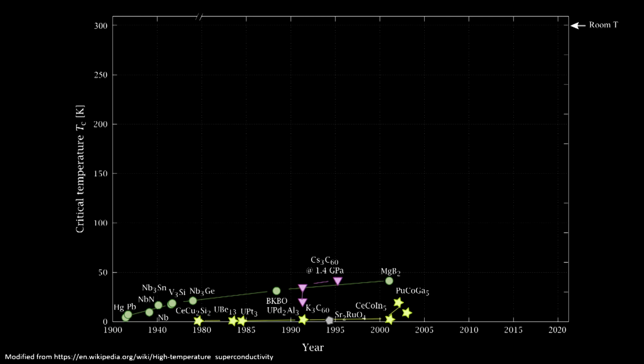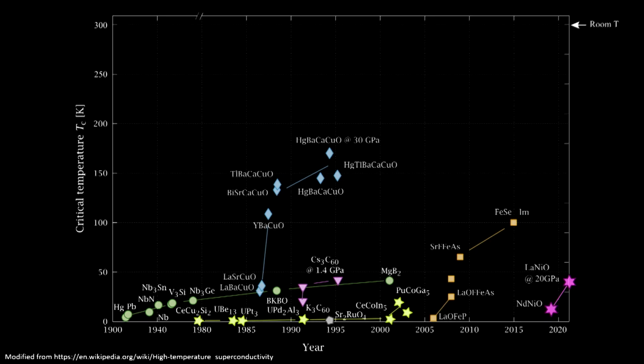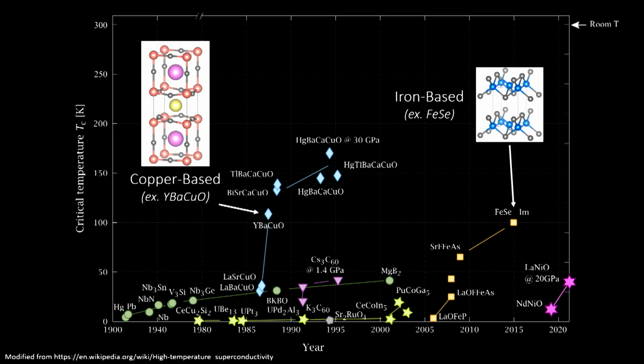This is because this conventional theory is a very weak coupling theory. Electrons don't interact very strongly with their lattices, and so these energy scales are actually rather weak, and they appear only at very low temperatures. But you'll see graphically that there are sharp departures in this timeline in the form of a series of unconventional superconductors: the high-temperature copper oxide-based superconductors, and the high-temperature iron-based superconductors. These show fissures in the phase diagram, fissures in the timeline, and they're guided by much larger energy scales related to magnetism, related to the spin degree of freedom of the electron, which can be very large.